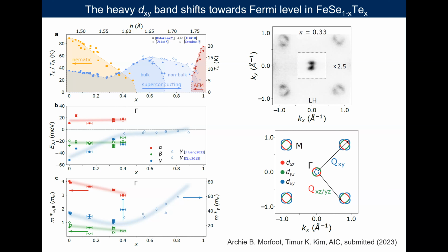Well, at the same time, the effective masses associated with this very correlated band seem to increase significantly as well. So it remains to understand how a correlated pocket, or a pocket which can give a lot of density of states, helps to boost the superconductivity from about 5 to about 12, 13 Kelvin. So quite a factor of 3. So yeah, these are the new results we have.